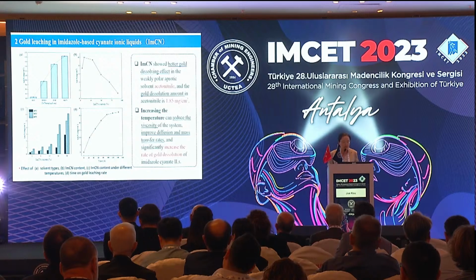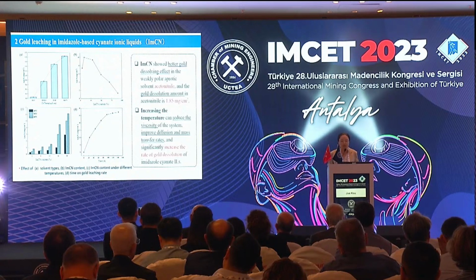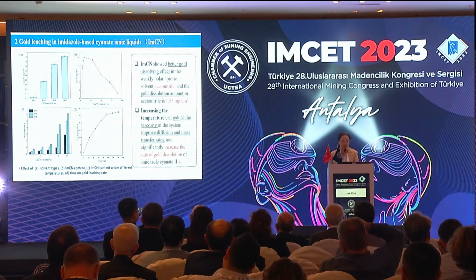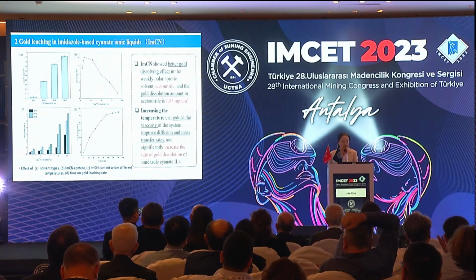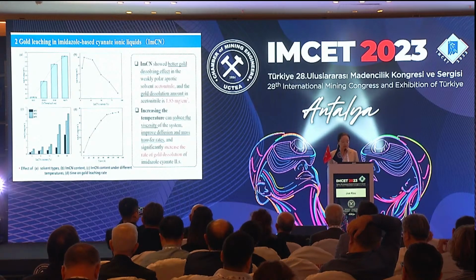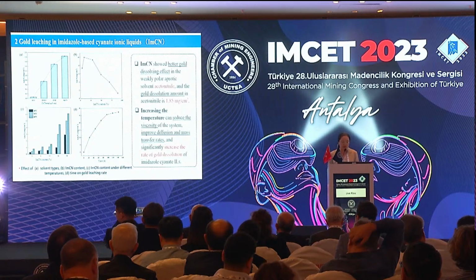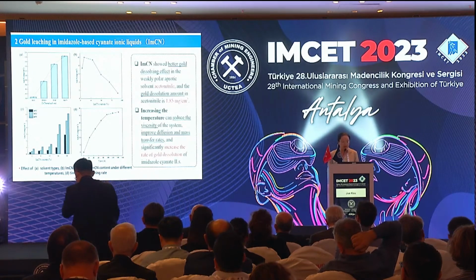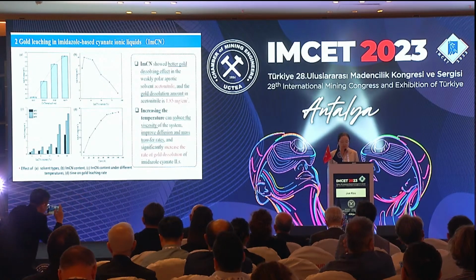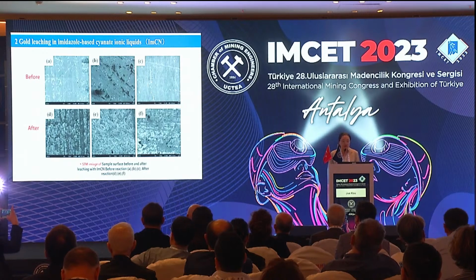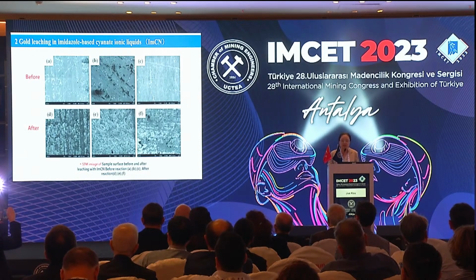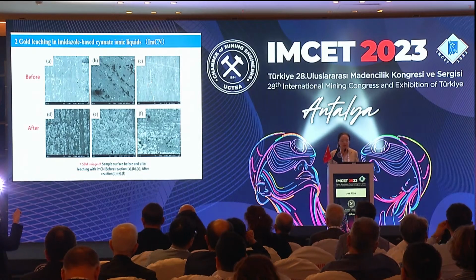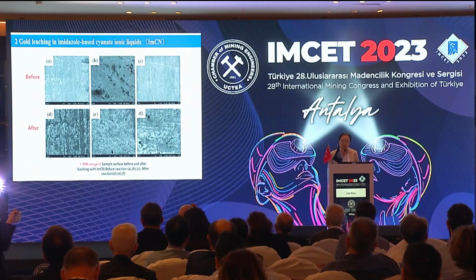And also we've tried different temperatures. Increasing temperature helps with the gold leaching, and it turns out that 60 degrees Celsius is much better. Therefore, it can help to increase the leaching rate. Also, this is the surface of the e-waste before and after the gold leaching with ionic liquid.